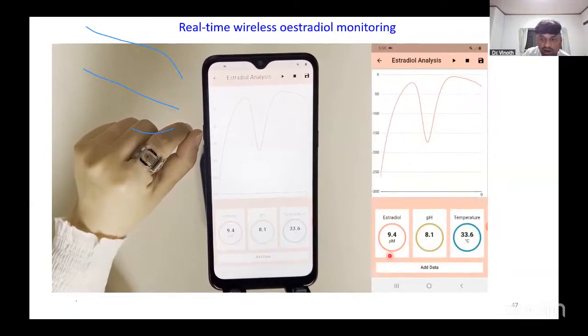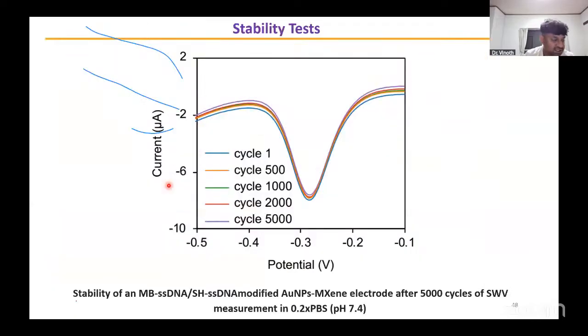From this sensor, we can identify the estradiol hormonal level as well as our body pH and body temperature. Also, the sensor exhibited excellent stability even after the 5000 repeated cycles in the PBS. This is the square voltammogram of cycle 1 and cycle 5000. It only shows a very small decrease in the current response.